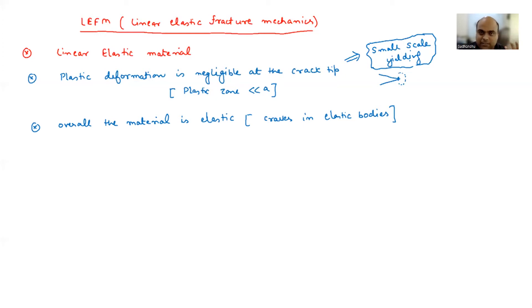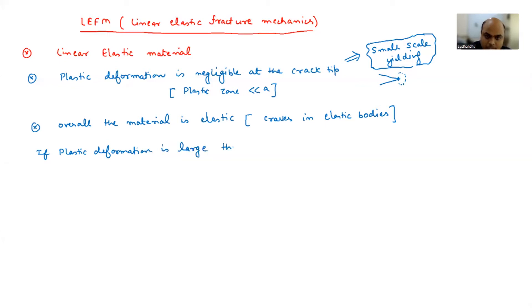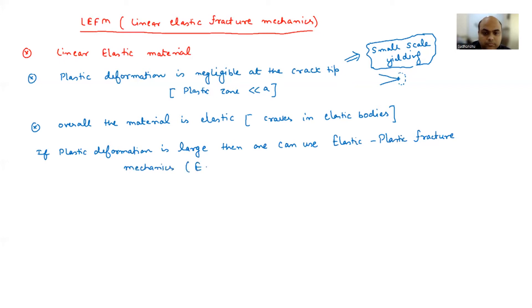Remember why we see yielding even if the applied stress is less than the yield stress — because locally you have stress concentration in front of the crack. If there is large plastic deformation, then one can use Elastic-Plastic Fracture Mechanics, or EPFM. We are not going to discuss EPFM in this course; we will mostly focus on the use of LEFM.